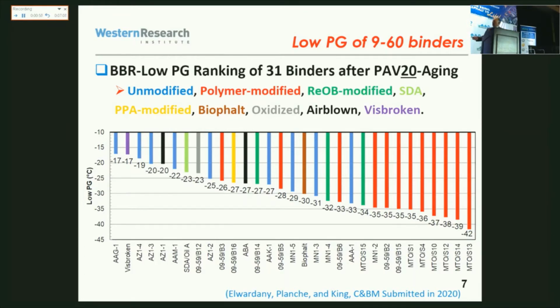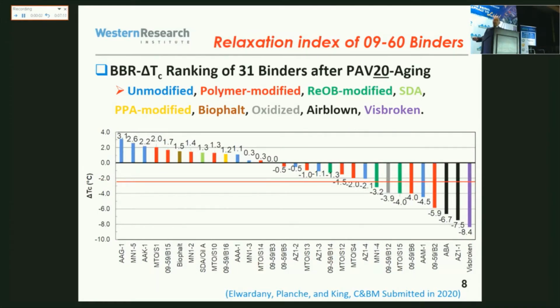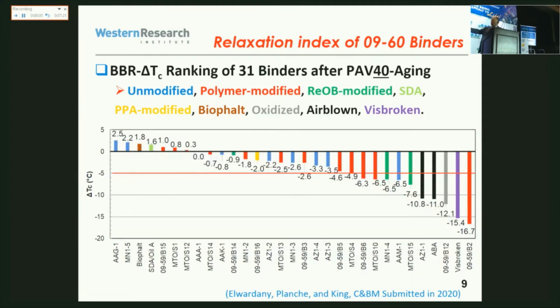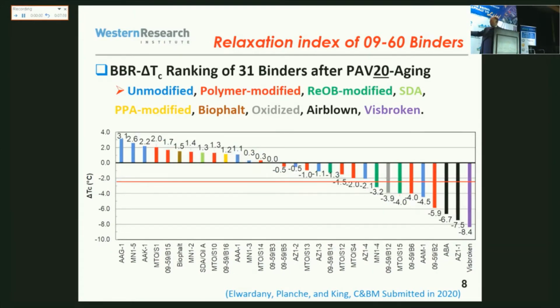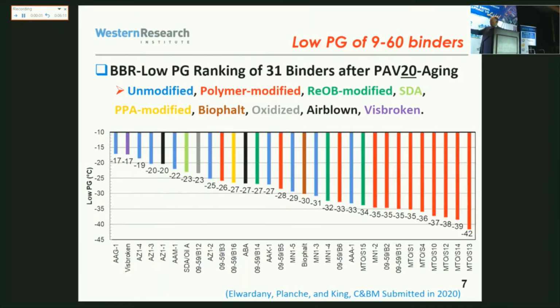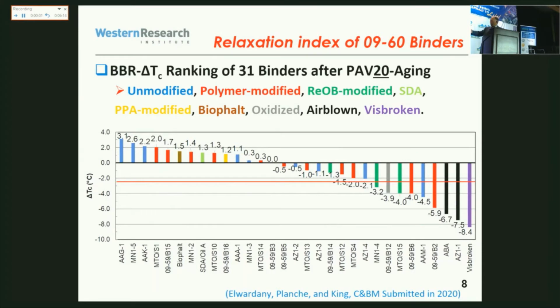Okay, now, what happens when we look at the Delta TC, which is a relaxation index, measuring the relaxation properties of the binder. And now we want this to be as high as... Okay, so that's the PG, all right. And so now the higher are good and the low are bad. And you see that, for example, polymer modified, which were all on one side, are now kind of evenly distributed here. So there is a different ranking for polymer modified asphalt, and also for all other products.